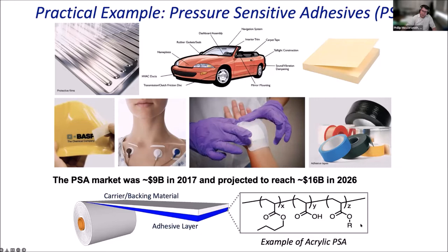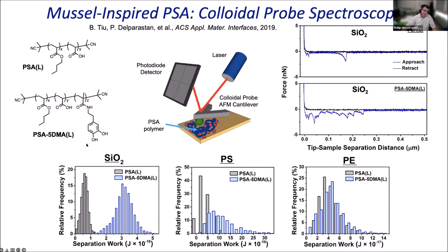These are often, not always, but often synthetic polymers. And we're interested in making these better performing underwater. Most of these actually are not great underwater. And I can illustrate one of the polymers that we have recently made. Sorry, there's a lot of data on this slide, but basically here's the polymer. It's a pressure sensitive adhesive polymer with, again, the mussel inspiration right here with the catechol in that polymer.